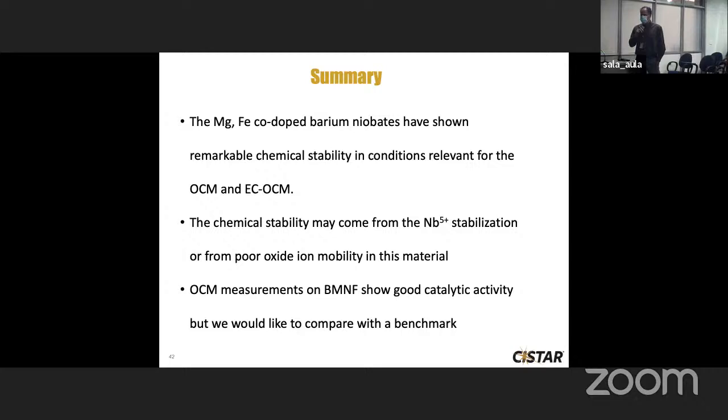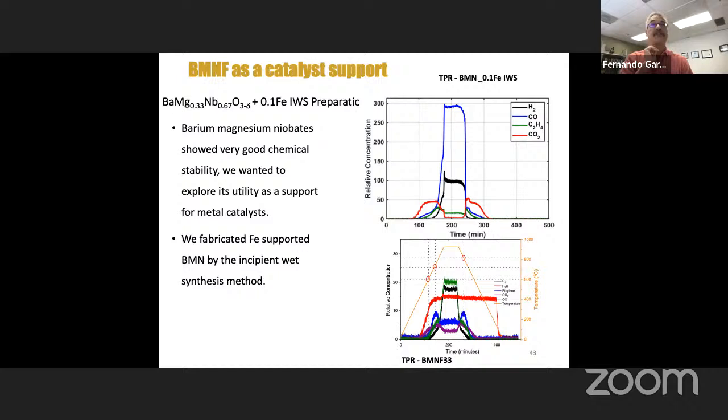Yeah, that's a very interesting question. We did not do the exsolving. We found that it was not necessary. We did reduce some of our samples and looked at the behavior, and we found that it really did not impact the behavior of the catalysis. And I actually have, just in case some of those questions were asked about this catalyst, we did do some deliberate studies where we added iron using incipient wetness to the surfaces of our catalysts to see how this would change the behavior. And we did similar types of experiments with the SFMO catalysts. And we found that it actually favored more complete conversion and decreased the ethylene yields, in contrast